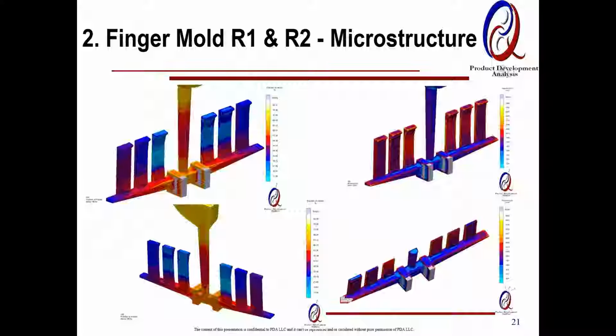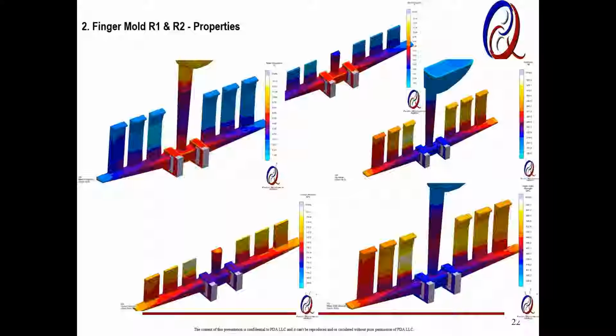So the point here is with the different section thickness, we obviously saw different solidification rate, different cooling rate, different gradient. As you would expect, this is the thinnest and this is the thickest, and when we went down further into predicting the microstructure, this is where you see fraction of ferrite, which is strictly driven by, for the same chemistry, a cooling rate. So the higher the cooling rate, you will have less ferrite and more pearlite, and that would have an impact on your properties, the most important being the elongation. As you can see, it's the same casting, same chemistry, different wall thicknesses.